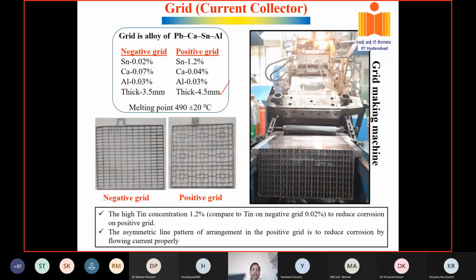So first is the grid. The grid is basically a lead, calcium, tin, aluminum alloy. More than 90 percent is lead, and a little bit of tin, calcium, aluminum is used to improve corrosion resistance. Generally the lead melting point is 327, and when you have this alloy, it is around 490 degrees centigrade. Pure lead melts at 327 degrees centigrade. I told you about different designs of positive and negative grids. These are made with a grid caster, and people even use some polymers afterwards to improve corrosion resistance. This is a metallurgy issue. Metallurgy people work on different kinds of alloys, on how to improve corrosion resistance and reduce corrosion.